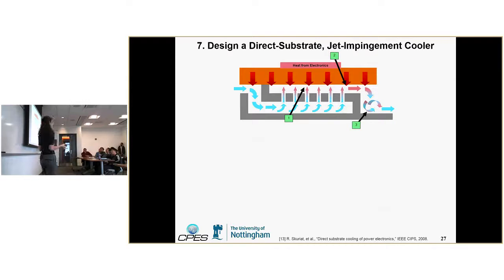So we're actually not using a base plate like you would typically use to spread out the heat in the power module. Instead, as you can see from this image, we've got the semiconductor die here, and this is maybe your ceramic substrate in our case. And so your cooling liquid will come here, and then you've got these holes that will impinge the liquid directly underneath your semiconductor device for more efficient cooling. Otherwise, typically it'll just pass underneath. This will actually impinge underneath the device, and then you've got your heat transfer happening in this area, and then the mixing of your working fluid.